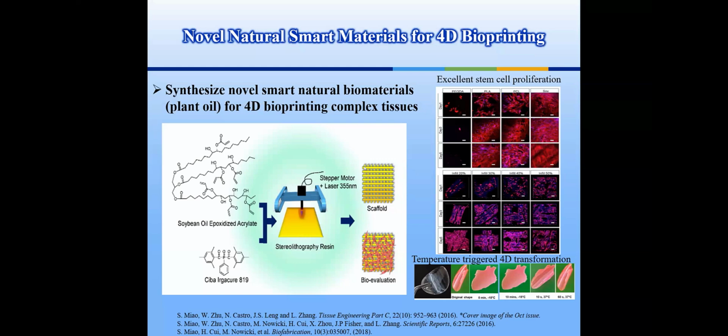So I think for PEG-DA, the cell proliferation is not ideal, but PCL and PLA are already approved by the FDA for many medical devices, drug delivery, and different applications. Our soybean oil-based material has biocompatibility pretty similar to those two materials, so cells can proliferate pretty well on our scaffolds. In addition, based on different designs like infill density, we can also print the structure pretty easily by